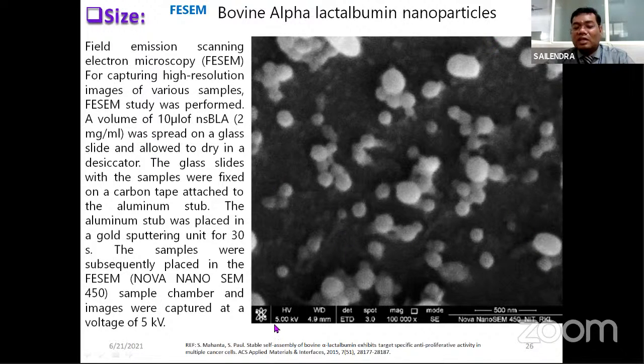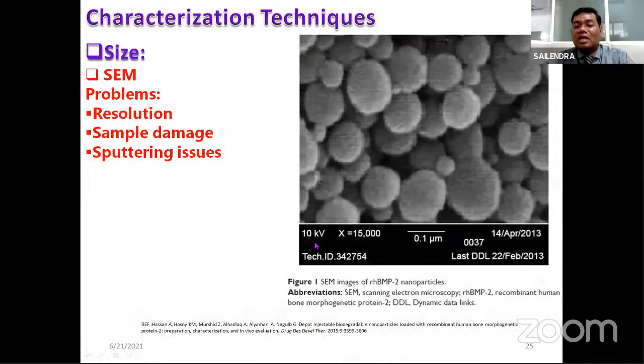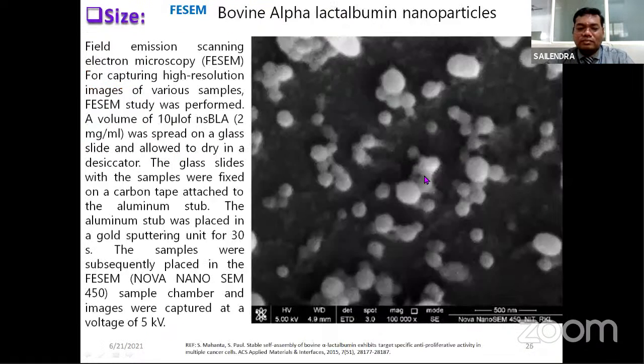Moreover, it requires very less voltage. As you can see, only 5 kilovolt energy is required, and that is why the chances of damage to the sample are very, very less. Whereas in case of SEM, you require 10 kilovolt. Somehow these researchers have got very nice pictures at 10 kilovolt. But as far as I have seen, at 10 kilovolt, when you are doing a scanning electron microscope and you go for a higher focusing image, you lose your sample.